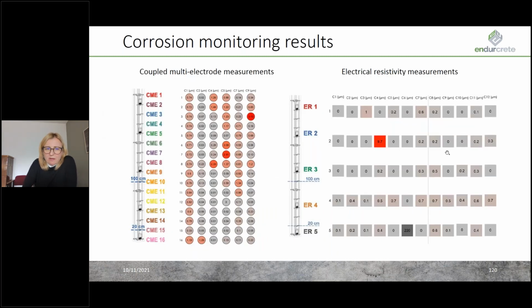Here we can see as well some of the results of the corrosion monitoring. Corrosion monitoring is continuously measured, as I said, with the embedded sensors and with the Wi-Fi data transmission system. The coupled multi-electrodes are along the whole length of the column, and you can see a little bit higher activity in the splashing zone, but this is still very low, almost insignificant corrosion activities.